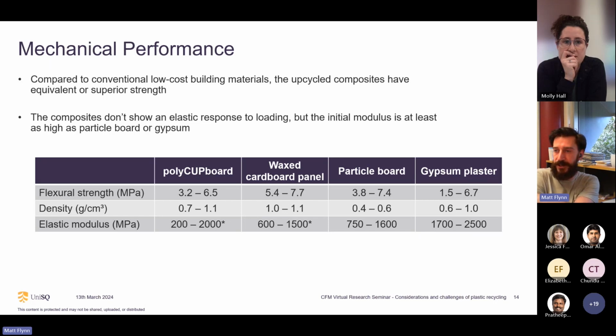So the materials that we've produced, they have not the most impressive mechanical properties, but they are in the same range as some of the paneling materials that are used for walls. So gypsum plaster, particle board, those sort of low-cost building materials that are high volume, and we get mechanical properties that are as good or better than them in some cases. So this is a really promising application for really high volume waste material that is quite simple and could also be implemented in regional areas rather than having to process everything in major cities.